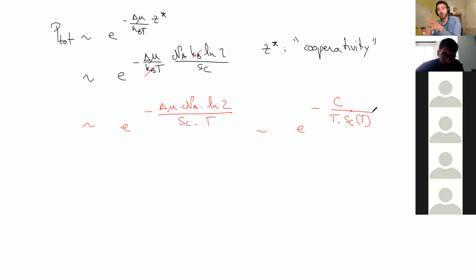So it's interesting. Now we are relating the probability of relaxation to a thermodynamic quantity, which is the configurational entropy, which is related to the number of conformations macroscopically the system has. And it can be a function of temperature, and we will estimate it based on thermodynamic arguments. So that is an important result. That's how the configurational entropy became a very central quantity in glasses. If you have an assembly of objects, pretty dense, can you estimate the number of allowed configurations? And this will be related to the ability to relax or not.